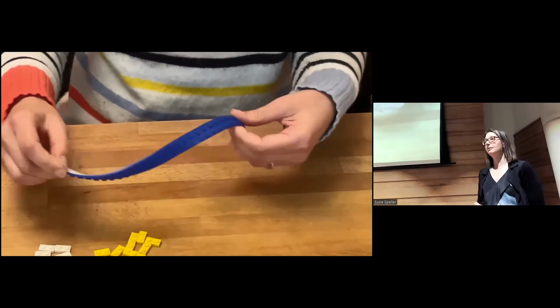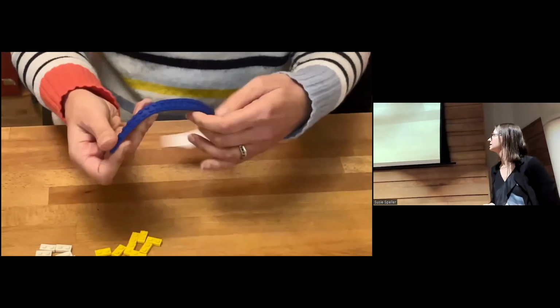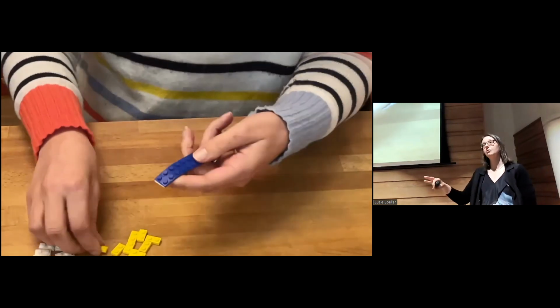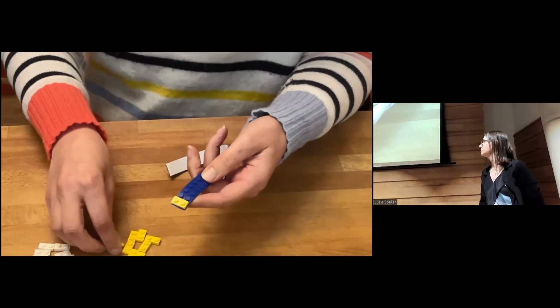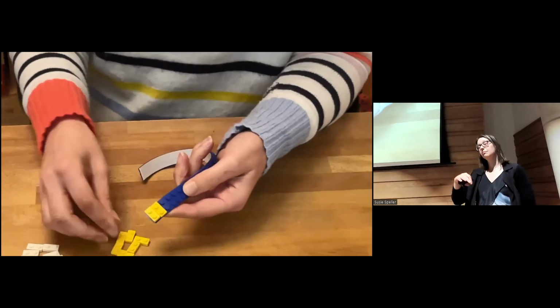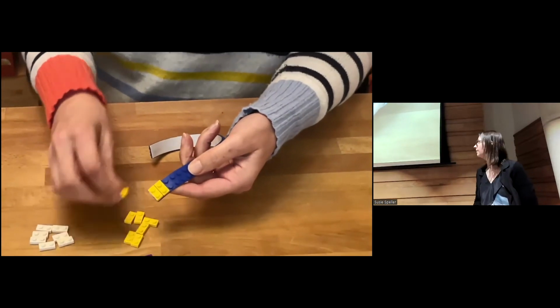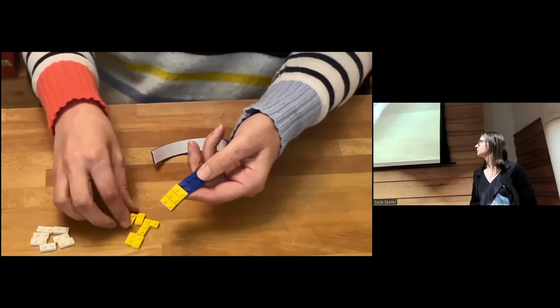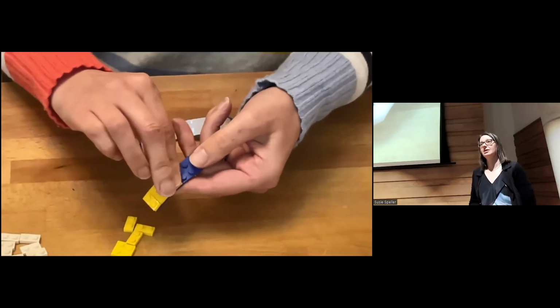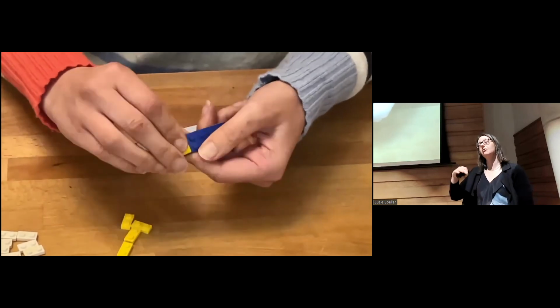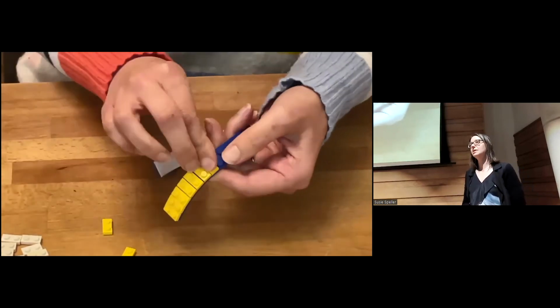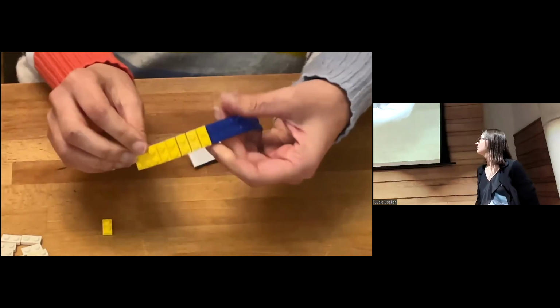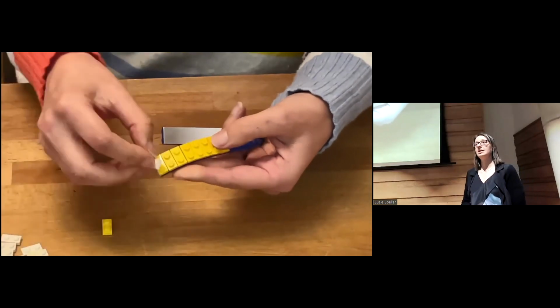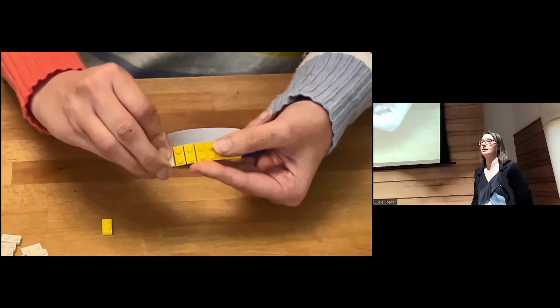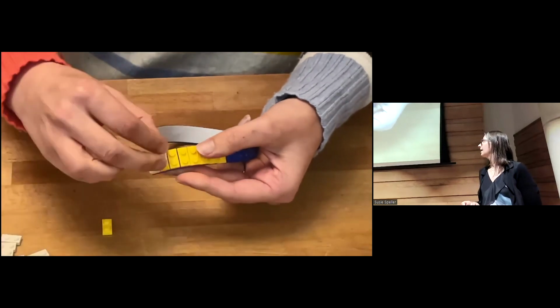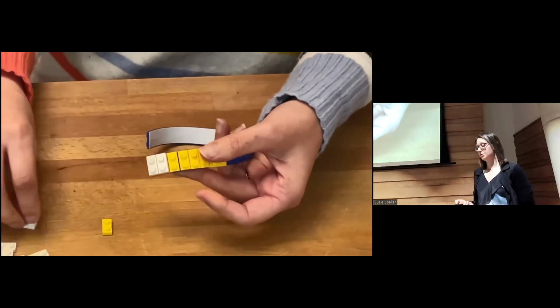You can do that in a metal. You can roll it and you can anneal it and you can get something that's pretty much nicely aligned with all the grains aligned. And then we deposit the layers, those buffer layers and the superconducting layer on top of it. But we do it in a very special way so that it matches the crystal structure. So whatever's underneath it follows that and it grows exactly on top of it with the same crystal arrangement. So if the thing underneath doesn't have any grain boundaries, then the thing on top doesn't either. And we do that one layer after the other to build up the structure.